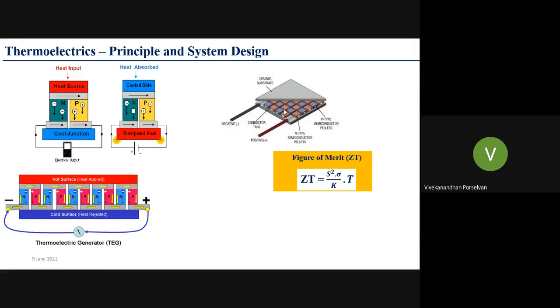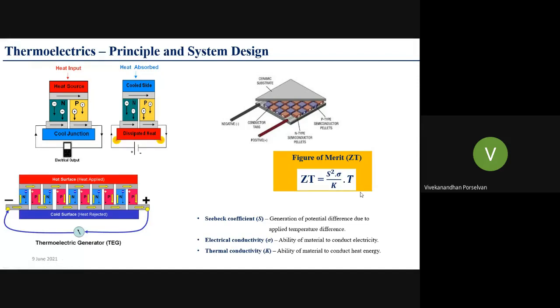So the efficiency of a thermoelectric couple or a thermoelectric material is designated by the figure of merit. Normally the efficiency is called the figure of merit when it comes to thermoelectric technology. That is designated by the term ZT, which is equal to S squared sigma divided by K at absolute temperature T, where S is the Seebeck coefficient, sigma is the electrical conductivity of the material, and K is the total thermal conductivity of the material.